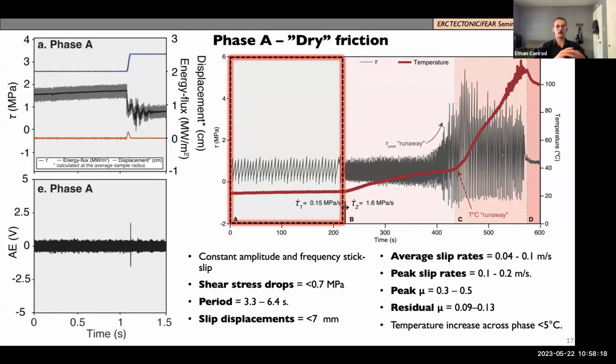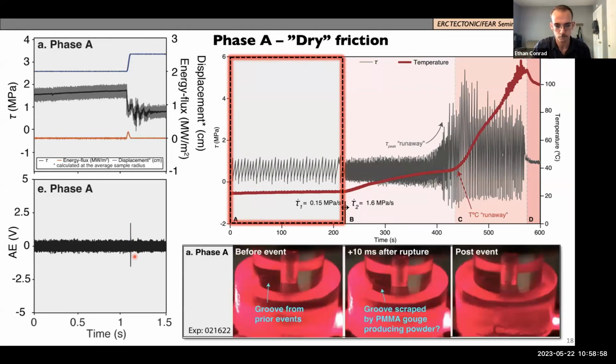Yeah, this is a good point to move on to, so kind of entering phase A. This is our first phase at the lower loading rate. I'm just calling this dry friction because it's without melt. And relative to the other phases, we see small slip displacements, a lower friction drop, and the energy flux is low relative to the other phases. The period is 3.3 to 6.4 seconds, and that becomes important when we increase the loading rate. And then in acoustic emissions, we see the small spike at this scale accompanying the slip event.